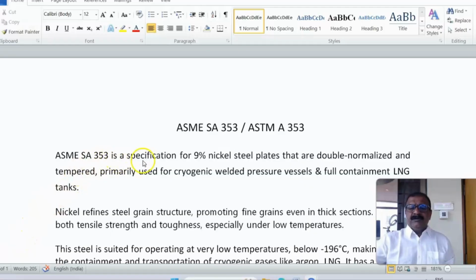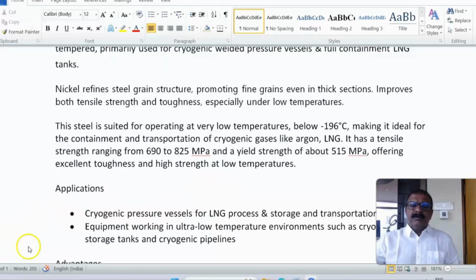ASME SA 353 is a specification for 9% nickel steel plates that are double normalized and tempered, primarily used for cryogenic welded pressure vessels and full containment LNG tanks. Nickel is a very important element which refines steel grain structure, promoting fine grain even in thick sections. It improves both tensile strength and toughness, especially under low temperatures. This 9% nickel steel is suited for operating at very low temperature, even below minus 196 degrees centigrade, making it ideal for the containment and transportation of cryogenic gases like argon and LNG.